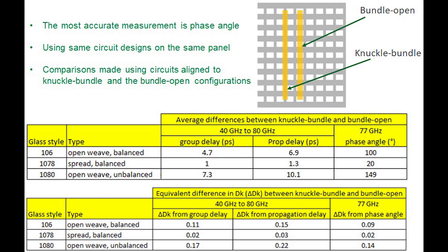weave effect. And then the other thing was the laminate itself is made up of PTFE and glass only, so there was no filler. So this is an unfilled system that was very thin, 4 mils thick, with no filler whatsoever, and glass and a pure resin system. That's also a worst case scenario for exaggerating the glass weave effect. We also use rolled copper.